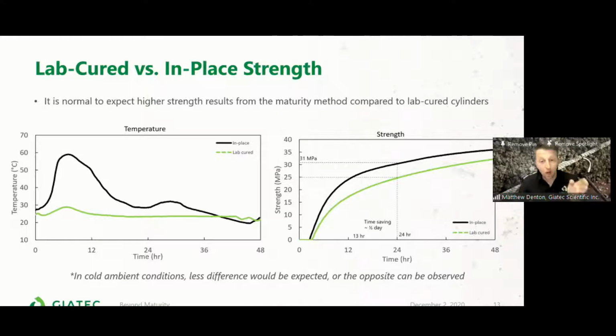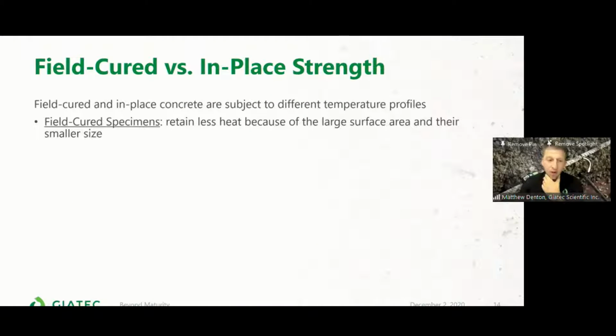So that's the concrete on site versus where we're taking a sample from the concrete and crushing that in the lab. We see that on the same timeline, at 24 hours, we're only reaching a 25 MPa strength. So you can see that there's almost half a day difference between the same strength results from the same concrete. And of course, the key here is that it's that spike in temperature that we see as a big difference. All right, so again, field cured versus in-place strength.